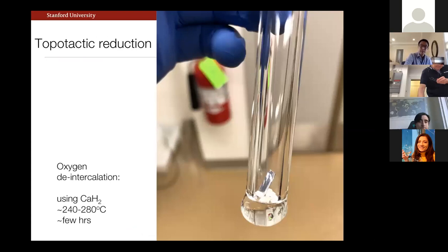The second thing that's amusing is the very key step for this looks something like this. Sometimes it's easier or nicer to show how it looks. This is how we're doing this oxygen deintercalation reaction. What you're seeing here is a 2.5 by 5 millimeter substrate with a thin nickelate film on top. Our current approach is to loosely wrap this in aluminum foil, mostly just for cleanliness or physical separation. These pebbles down here are calcium hydride, something like 100 milligrams of that in an evacuated glass tube. And we're annealing this at a few hundred, to 250 degrees C or so for a few hours. So despite the rather expensive and fancy UHV equipment that I showed you in the previous slide, this is a key step. It's very modest looking, but trying to sort this out, frankly, from our end, mostly empirically, was one of the key aspects of this work.